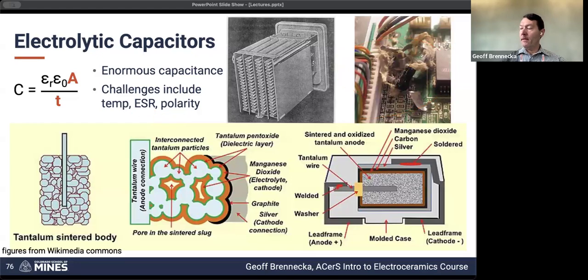connected electrode. So I mentioned aluminum and tantalum. These are the two most common versions. There are wet and there are dry versions. So you can actually have an electrolyte that stays in the capacitor body that can increase the performance, but it can also very much limit the temperature stability, because if you've got a liquid that's going to be very responsive to temperature, you don't want to boil it. Again, you end up with a pressure buildup and explosion. So dry electrolytic capacitors are generally going to be a little bit more flexible in terms of temperature and voltage operation than the wet versions. But again, these are broad statements. So this is one possibility.